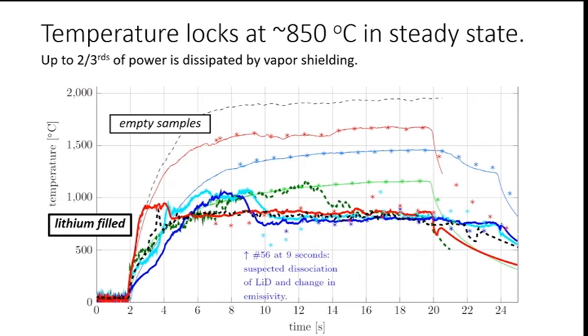And the striking thing is that, of course, the empty samples, if you increase the power gradually until 16 megawatt per square meter, which is very significant, of course, the temperature of the samples increases. While for the lithium, this doesn't seem to be the case. The temperature is fixed. There is no change in temperature for some reason. And the reason is vapor shielding.